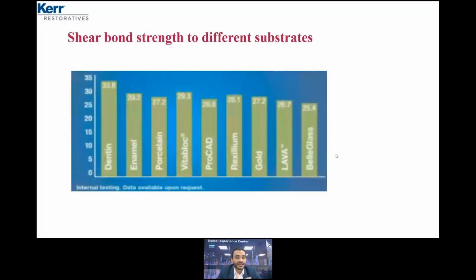As we mentioned, in Nexus we have a high bond strength. Why? You can see here for the dentine, for enamel, porcelain, gold, lava, most of the substrates, most of the restorations, at least you have 24, 25 as a value.